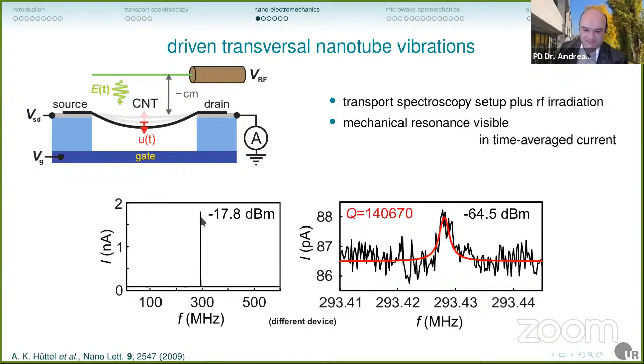And then you can zoom in, you can go to lower signal levels, and at some point you see this is a very, very sharp resonance with a mechanical quality factor of somewhere around 150,000 in that case. This was the first measurement where this was shown. That's already 12 years ago. And in the meantime, people have demonstrated that you can reach mechanical quality factors with carbon nanotubes in the millions, 5 million, 7 million or so.